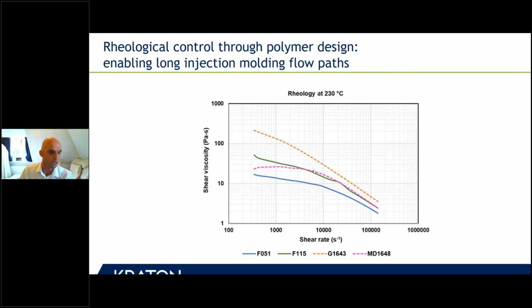And now if you make a compound, and the green line is giving a classical Kraton G-based compound, and the blue one, a compound that was developed for IMSS, you can even reduce this a bit more. And by tuning this viscosity at a certain shear range, you can reach the long flow paths that are needed for such a large object and with such thin walls.